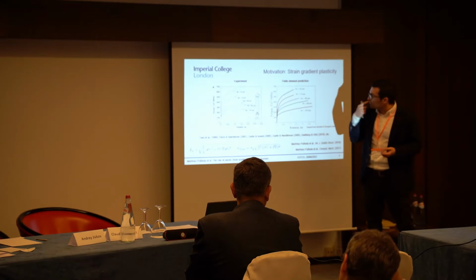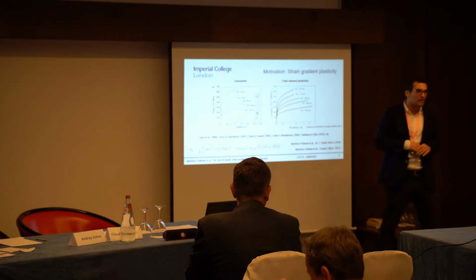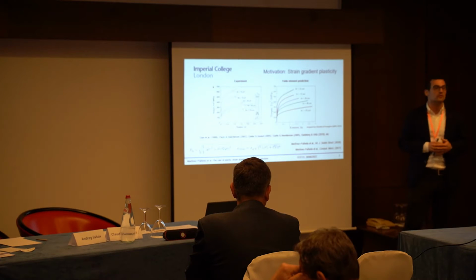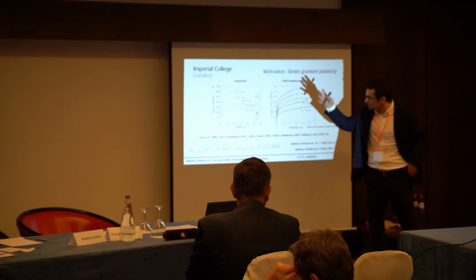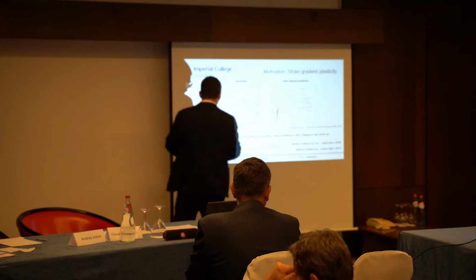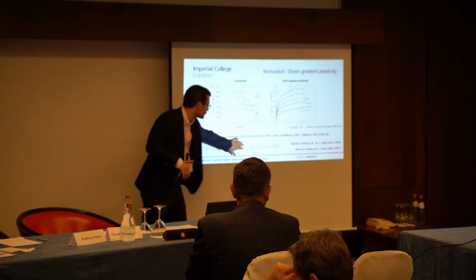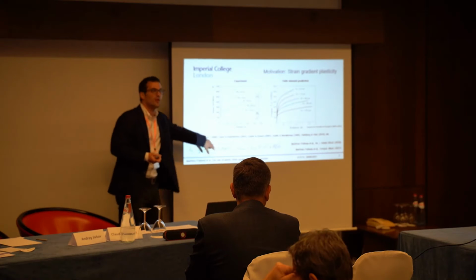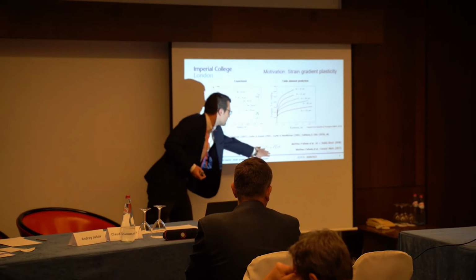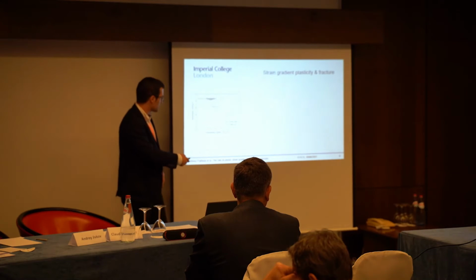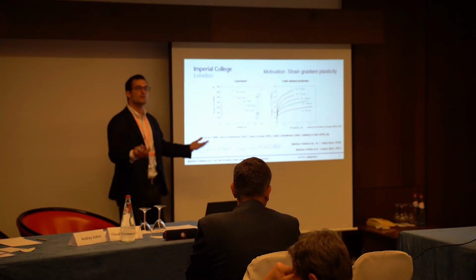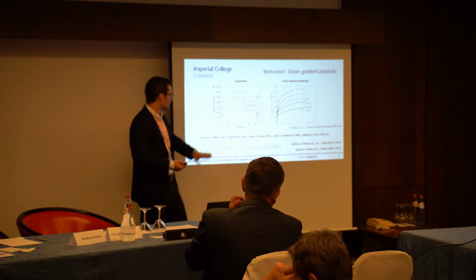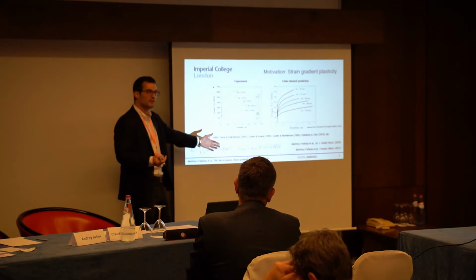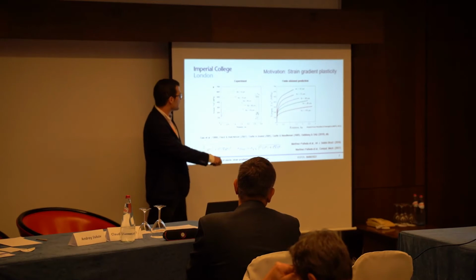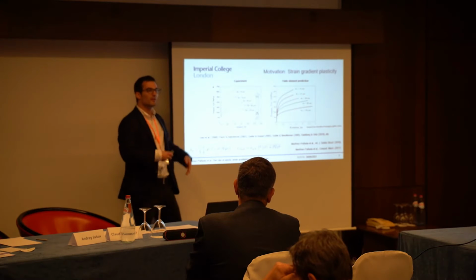And the good news is that a good number of famous mechanicians have devoted their efforts to extend plasticity theory to small scales by developing what are called strain gradient plasticity theories. And the key step, I would say, in building these theories is that you define the plastic work or the flow strength not only as a function of the plastic strains, like in a conventional theory, but also as a function of the plastic strain gradient. And in this way, you introduce, through dimensional consistency, a length scale into your model. So if this length scale is equal to 0, you recover conventional plasticity, but otherwise, by fitting this length scale to the experiments, you're able to capture, as you can see very well here, the response that you would expect.